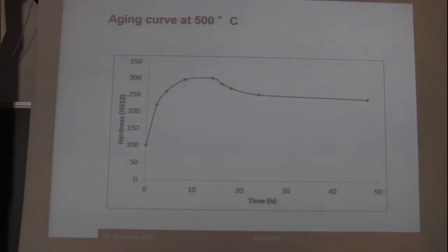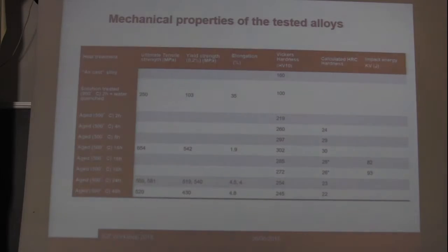After that, we performed solution treatment at 900 degrees centigrade and water quenching, and then we performed aging. As you can see from the diagram, hardness reaches maximum values between 8 and 14 hours, and then it decreases due to overaging. After that, we tested the mechanical properties of the selected alloy.